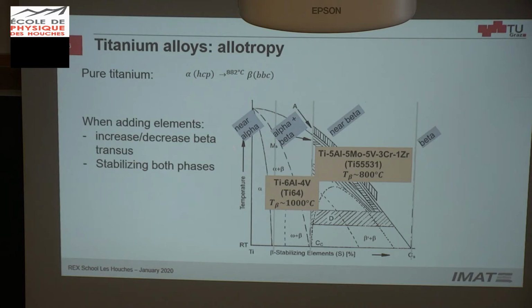And by adding some alloying elements, we can stabilize the high temperature phase, and we can also decrease the transformation temperature of this beta transus, and most of the titanium alloys have this type of configuration, where you have the temperature and the beta stabilizing elements. Also you have alpha stabilizing elements like aluminium, for instance, which would move the whole diagram upwards. And then you have a mixture, or a dual microstructure, so alpha and beta. So a very complex situation for deformation. These materials are processed either in beta or in alpha beta. And this makes everything very complex when we want to understand it, control it, and then model it.